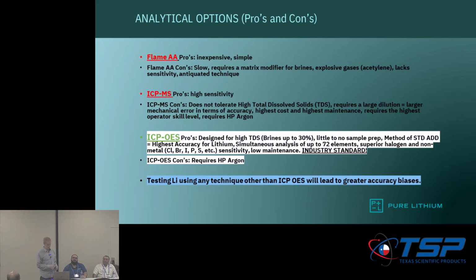ICP-OES is what we homed in on, and almost everyone in the industry uses. I'd say it is the preferential technique for this. You can cram up to 30% total dissolved solids. You can run organics. So when you're talking about an electrolyte, you can run EC, you can run DMC, dimethyl carbonate, all these electrolyte materials, you can pump directly into the ICP. You can calibrate it using isopropyl alcohol and aqueous standards, and you get a pretty good matrix match. You can run the alloys, so if you're doing a copper substrate or an aluminum substrate on the cathode, you can digest that and run it into the ICP.